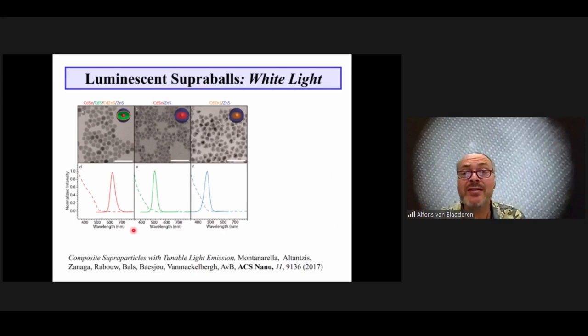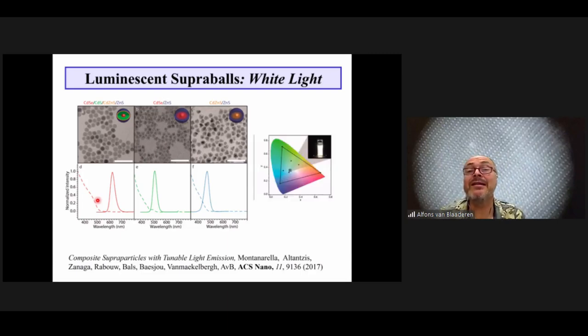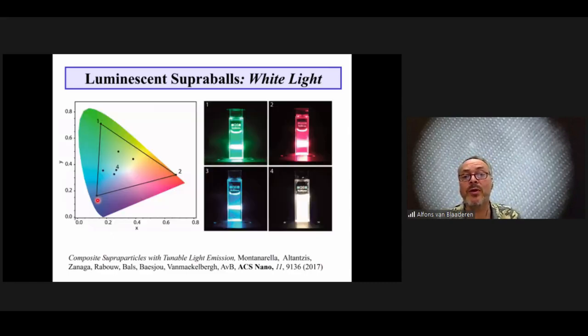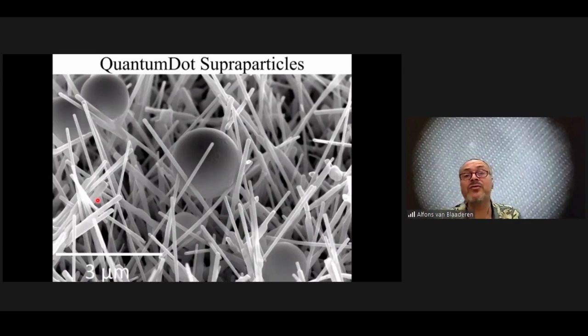Well, for trivial reasons, you can build up these supraparticles with red, green, or blue quantum dots, and then make any color that you want. And you've probably seen that, and we're not sponsored by them, some televisions have much more beautiful colors if you use these quantum dots. They are much more easily processable if we make these quantum dots in a supraparticle. So that's what we did, and just as an example, we made these beautiful white supraparticles by mixing the right red, green, and blue colors inside the supraparticles. And here you see some of these other supraparticles.